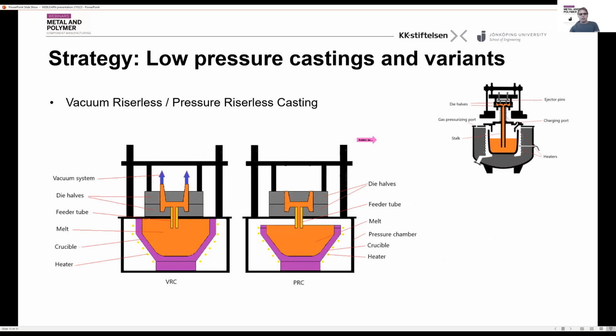There are some ways of improving the low pressure die casting process, and there are the vacuum riserless and the pressure riserless casting system. So for the vacuum riserless system, you have a hermetically sealed compartment above the actual die system, where you suck up the melt through vacuum into the die cavity. There is also the pressure riserless casting, where it's just as for the low pressure die casting system, a compartment where you increase the pressure and you force the melt up.